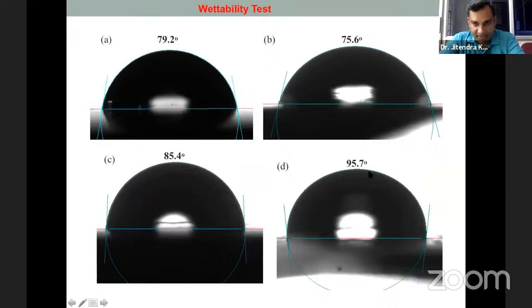In that, I see that SU8 HBN with PFP gives a more hydrophobic surface, and AFM analysis also shows nanotextures, and those nanotextures help make the surface very hydrophobic. This surface also gives me better wear resistance and a lower friction coefficient. So this wettability analysis is required for checking the surface energy and the nature of the surface, whether it is hydrophilic or hydrophobic. So these are a few surface treatment processes which I showed you.